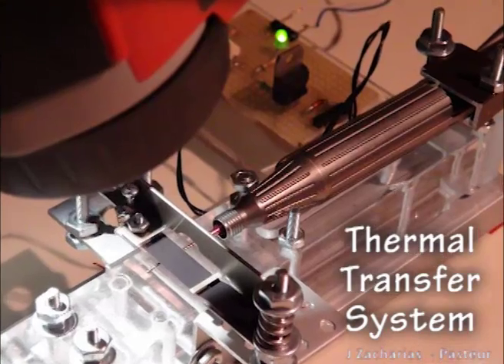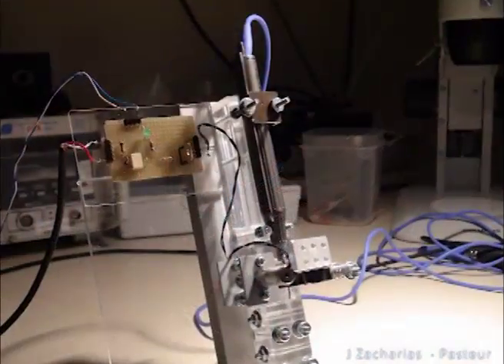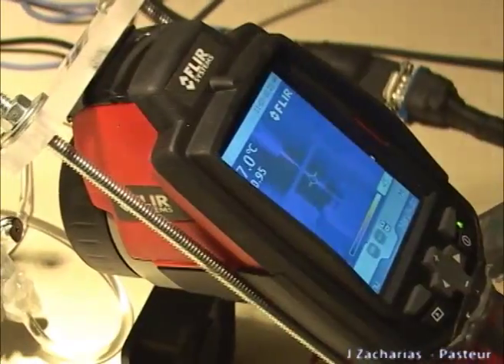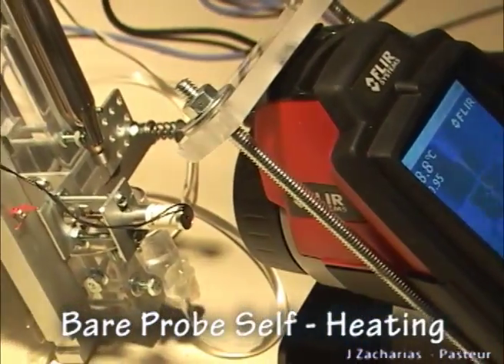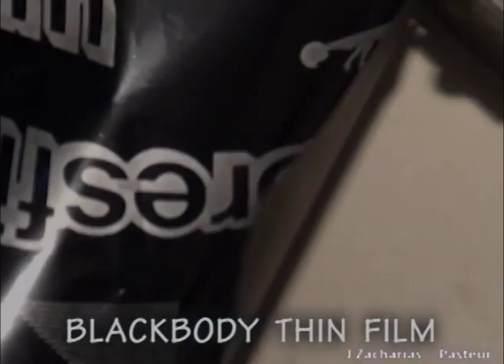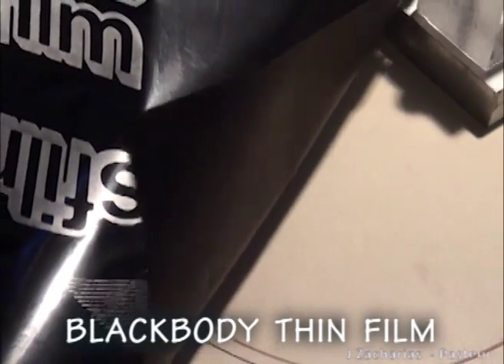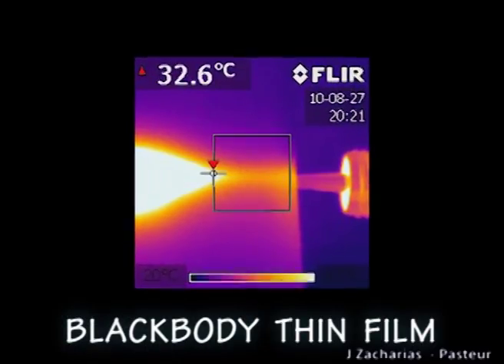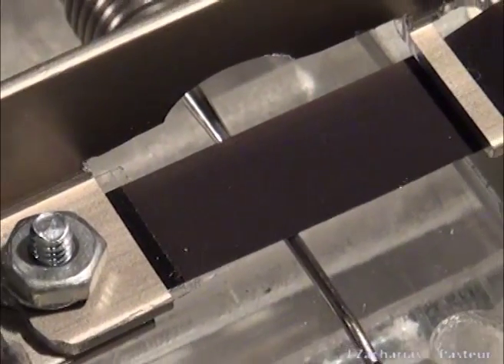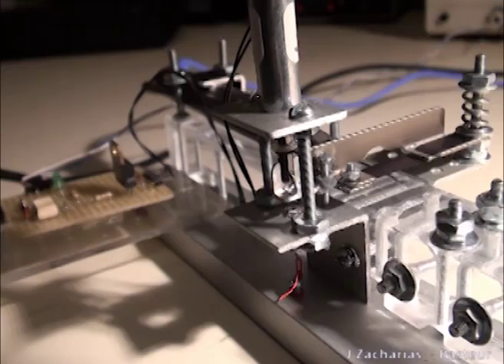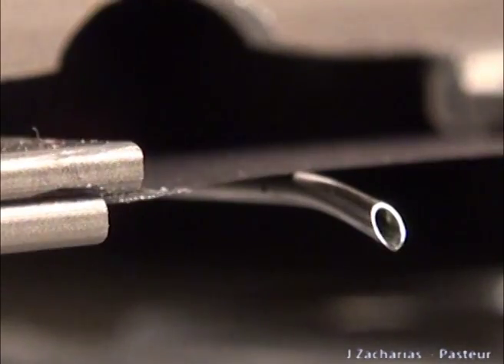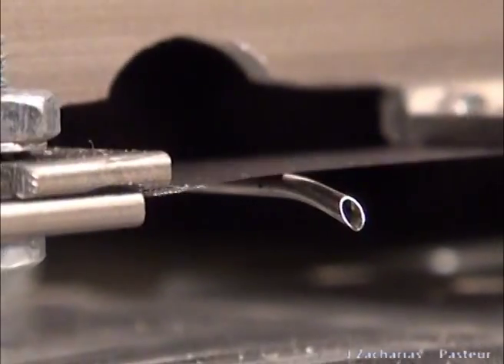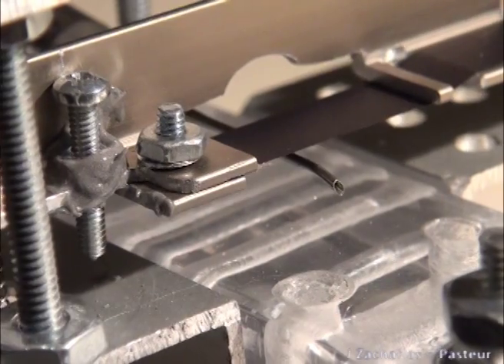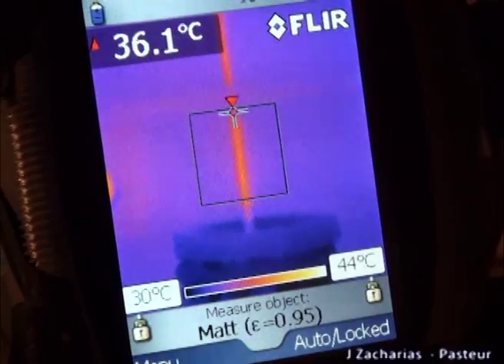We designed a thermal transfer system to examine bare phaco probes in search of zones of self-heating by ultrasound. A thin film with emissivity near 100% and with low thermal capacity was incorporated as a thermal screen. An electromechanic system using computer control was built to put the thin film in contact with the probe shaft only between periods of oscillation to avoid friction.